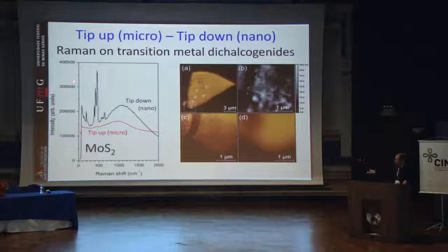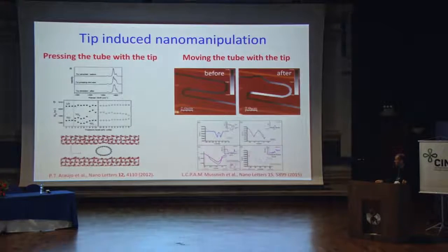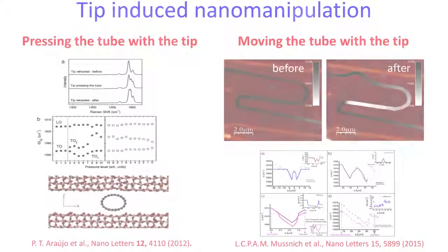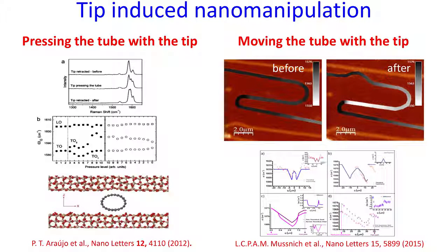And then when you land the tip on top of MoS2, the signal enhances significantly, and you can do imaging, and you compare this image with this one, and do all the sort of information that you can extract with Raman spectroscopy. Since you have a tip to enhance the local signal of the material, you can also do nanomanipulation if